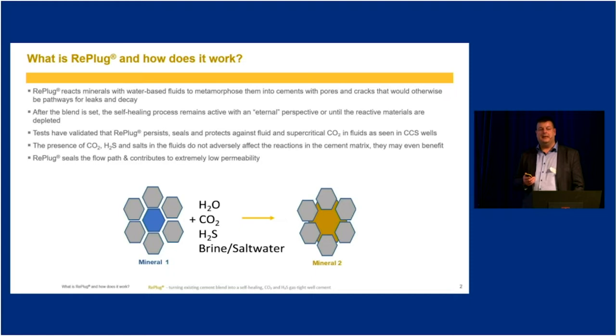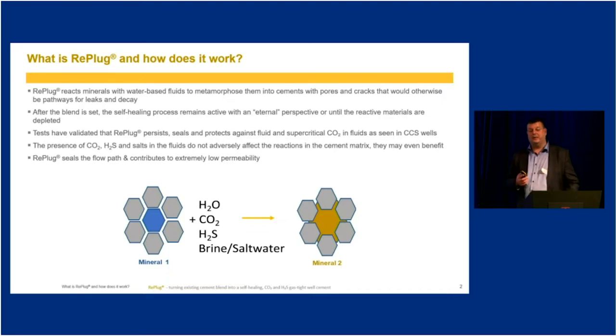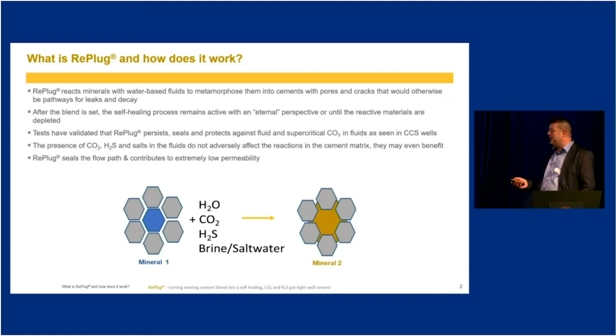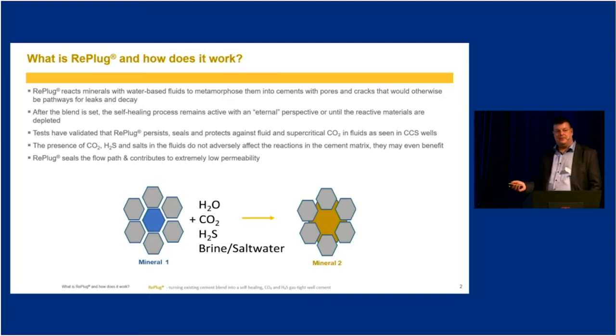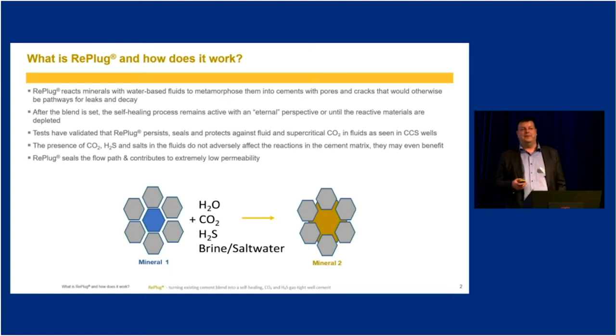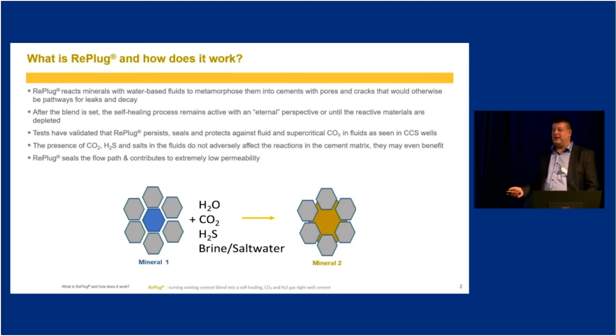This continues until you have fully exposed it to the maximum expansion, which is about 30% by volume. For getting this to expand, you need water — any form of water, brine, salt water, fresh — as I said. You don't have to have CO2, but it doesn't do any harm either. It's actually beneficial to have CO2. And it's also inert for H2S, so H2S won't affect it at all.